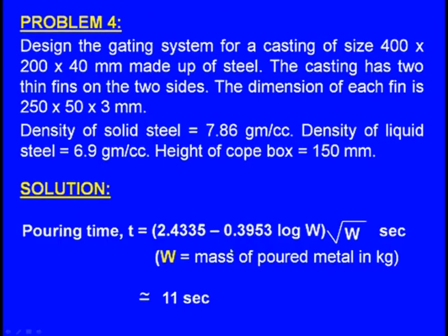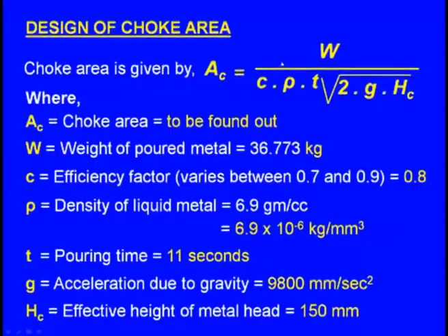And if we substitute the mass of the poured metal in this formula, we will get the pouring time as 11 seconds. Now, we are going to design the choke area. Choke area AC is equal to W divided by C rho T root of 2GHC. AC is the choke area, and we need to find out that W is the weight of the poured metal, that is equal to